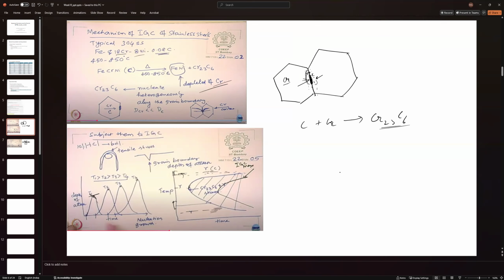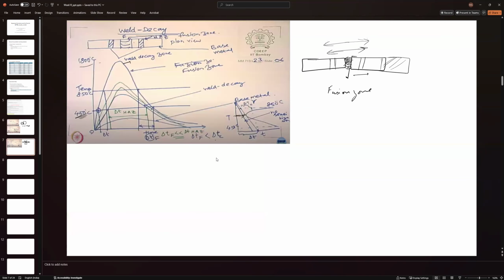Right? So this region is around the 400 to 850 degrees Celsius region. It will depend on different alloys, but for this case, once you reach 450 degrees Celsius, you'll start forming these precipitates. Okay, so that's far away, and near the fusion zone, what will happen is the chromium carbide precipitate